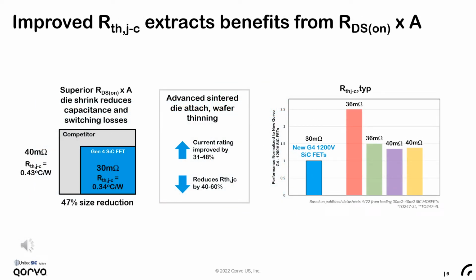In order to extract all the benefits of the improved RDS(on) times area, we've improved the thermal resistance, which maintains a good current rating despite the die shrink that affords the performance advantage we cited previously. By employing an advanced silver sinter die attach, along with further wafer thinning, we're able to improve the current rating by 31 to 48% and reduce the thermal resistance by 40 to 60% for a given die size.